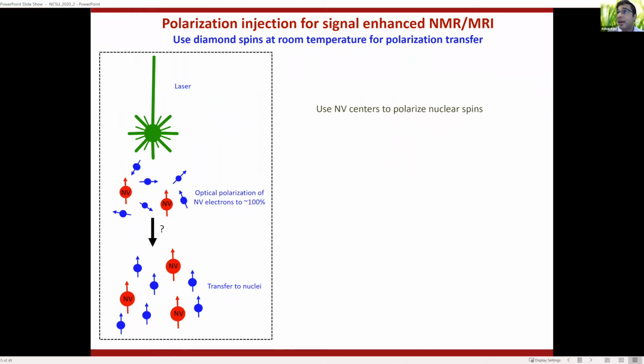You just buy it. And it's compelling to consider whether you can take these NV centers, shine light on them, so they align, they spin polarize 100%. But if you've got nuclear spins in their surrounding, then they are not polarized at all. So even at something like 7 Tesla, the polarization, which is the alignment of these spins, is only a few parts per million.